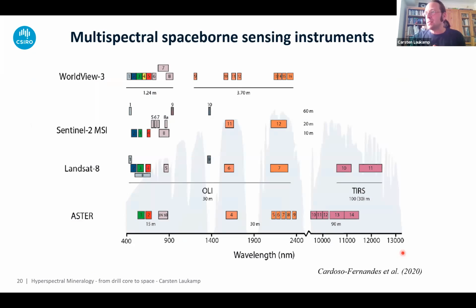Which brings us to ASTER just quickly. We've got here the wavelength range on the x-axis between 400 and 2,500 nanometers, and then we do a little jump and look into the thermal infrared. Highlighted here are the bands that are collected by ASTER. So it's a multispectral system. We've got only 9 bands in the whole wavelength range between visible near and shortwave infrared, in contrast to hundreds of bands, or close to hundreds of bands, in the HyLogger. And this is where the bands are located, and you've got a few more bands in the thermal infrared also. The reason why these bands are collected there is because that's where our mineral absorption features are. So ASTER is what we would call maybe a geoscience-tuned spaceborne system.